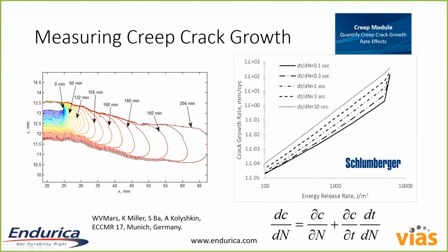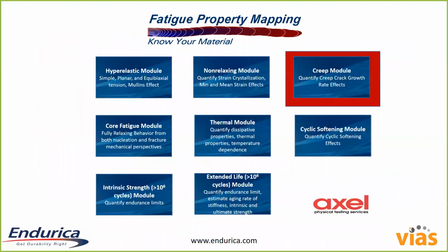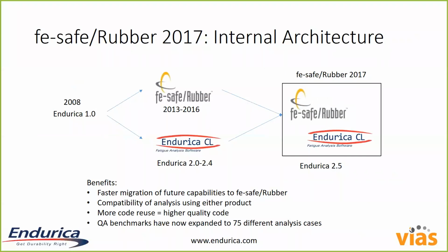And this phenomenon is important in problems where you have high loads that are present for long periods of time, as you might in downhole applications where you have very high pressures and high temperatures. You're leaving a seal in place for the life of the well. So this is a new experiment we can measure, and then these parameters go right into the code. So that's what's new on the experimental side.